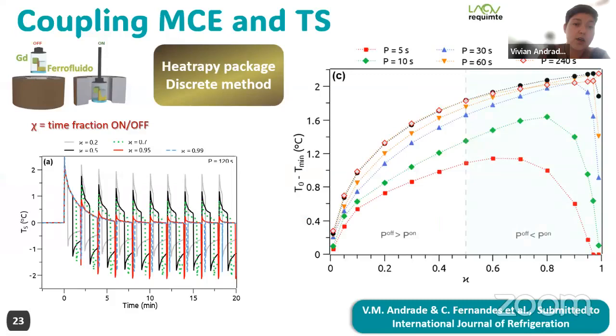We performed also simulations using the Heatrapy package in the discrete method. And if you look here, we have this term, the ratio between the time fraction in the off state. For higher periods, as we have here, 240 seconds for instance, there's a limit where this value tends to reduce. So of course, there is a gain when we give less time for the material to heat up, but we have a limit where this will work or not.